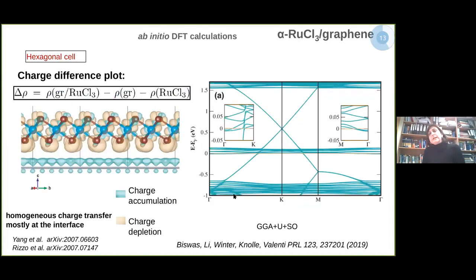Now when we calculate with these heterostructures, what we find is that there is an important charge transfer between the layer of graphene and the layer of ruthenium trichloride. Graphene gives charge to ruthenium trichloride, so we end up with a hole-doped graphene and an electron-doped ruthenium trichloride. This has also been observed experimentally, and it is happening here at the interface.